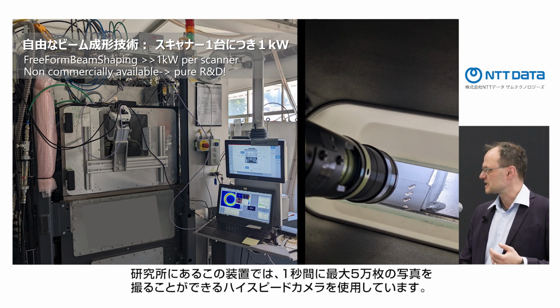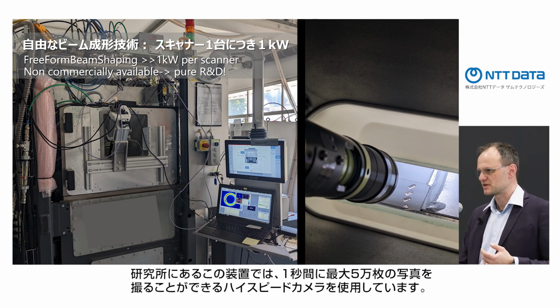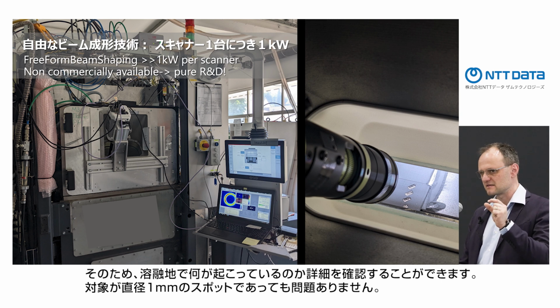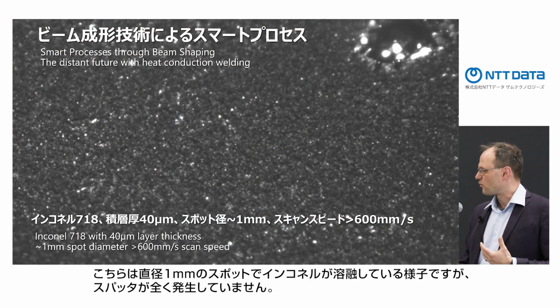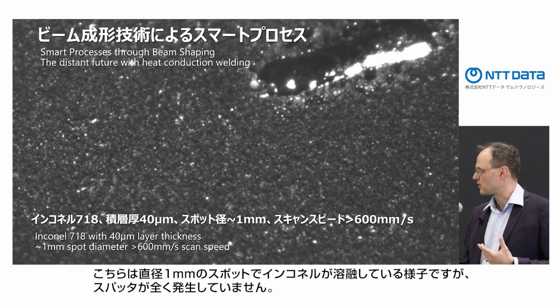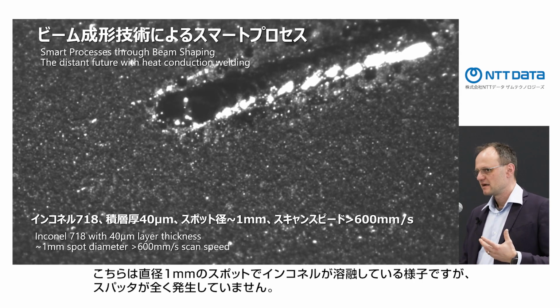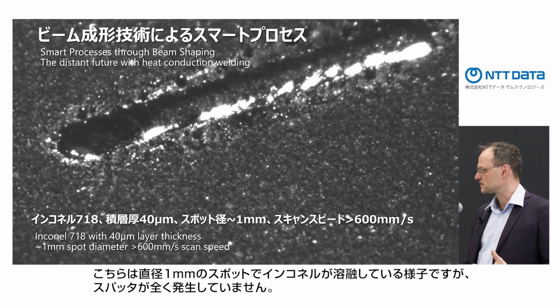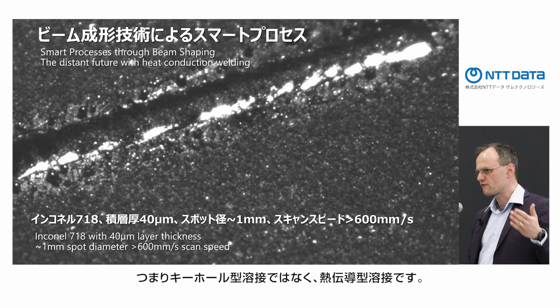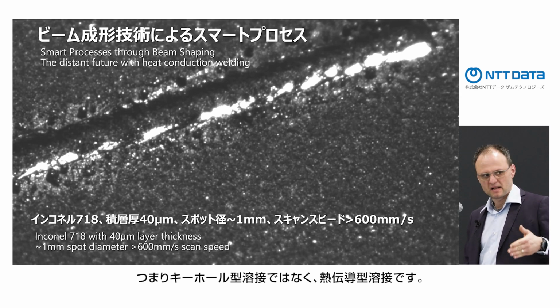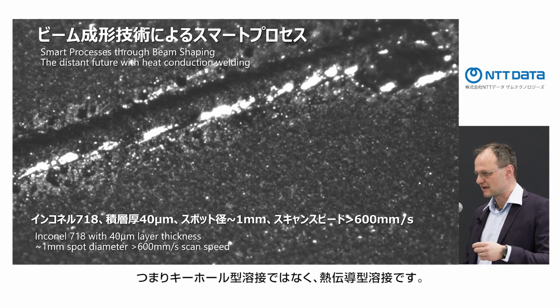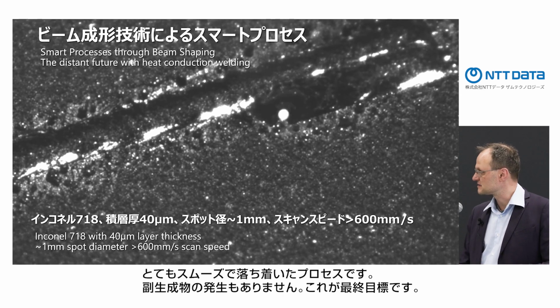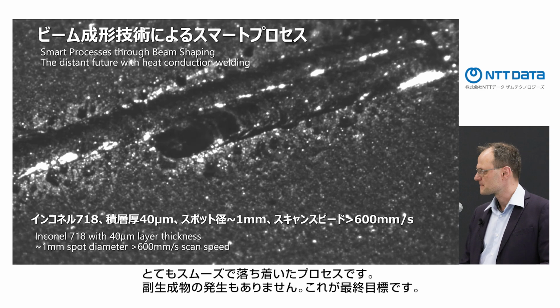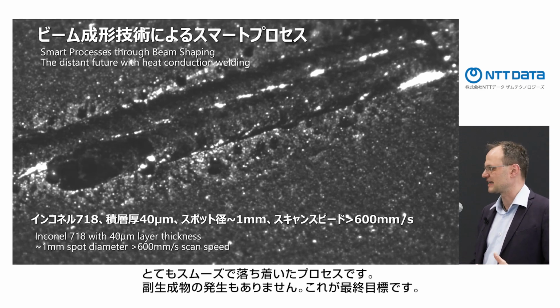On that system, there's a high-speed camera that can take up to 50,000 pictures per second, so we get a very detailed view of what is happening in the melt pool. And we've been able to demonstrate that we can, even with a 1 millimeter spot diameter, so this here is a 1 millimeter spot in diameter, melt Inconel without spatter formation at all. So this is heat conduction welding. We go away from the keyhole welding, from the deep melting of the powder, to heat conduction welding. It's a super smooth, very calm process. It has no side products, it has not ejected anything.